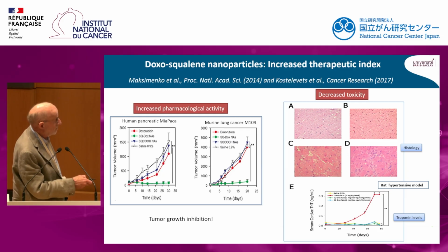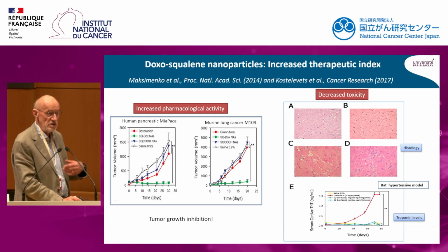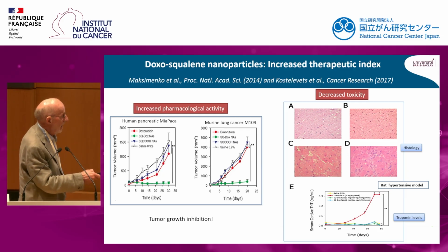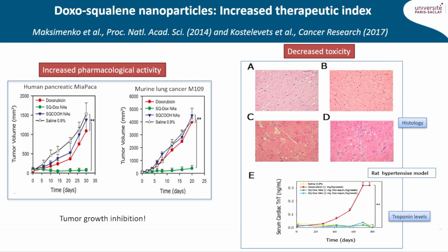You can see, of course, here in red that the administration of doxorubicin as a free drug is associated with a huge increase of the troponin level, which is a marker of the cardiac toxicity. And after taking some biopsies, you can see very clearly the vacuolization of the cardiomyocytes.